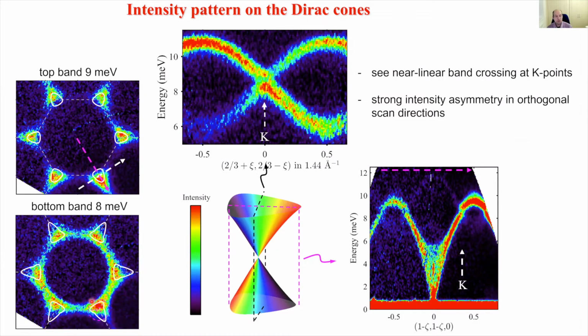Now, another way to see this intensity asymmetry is to focus at a constant energy and look at the intensity distribution as a function of momentum. So in the top band, it's all on the right-hand side in this diagram, which corresponds to outside the first Brillouin zone. So all the intensity is on the outside here. Whereas if we go to the bottom band, it should have moved to the inside. And indeed, all the intensity has now moved to the inside.